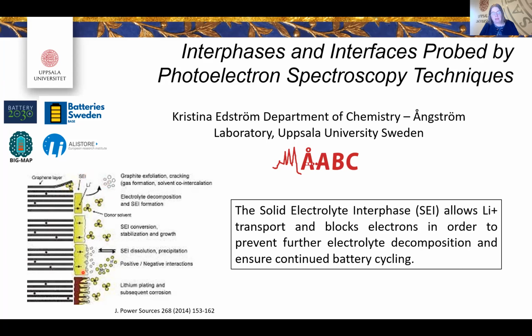We are at potential very close to that of lithium. Lithium is the one which is at the far end of the electrochemical series, so it's very difficult to stabilize it. But on graphite, you can do it with this SEI, as we call it. But this SEI also converts and stabilizes where the lithium is intercalating and deintercalating through this layer, because it has to allow lithium transport. And you also have some dissolution. You can have lithium plating. I saw there's another presentation on that at this conference, which is an extremely important thing, and subsequent corrosion.